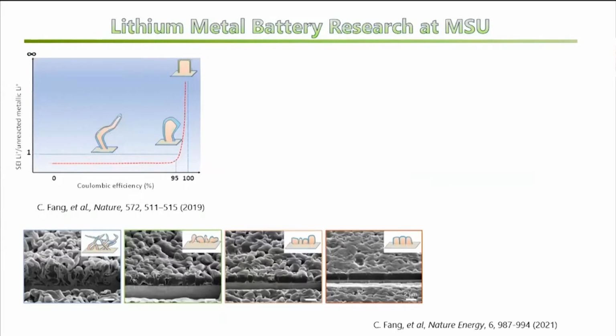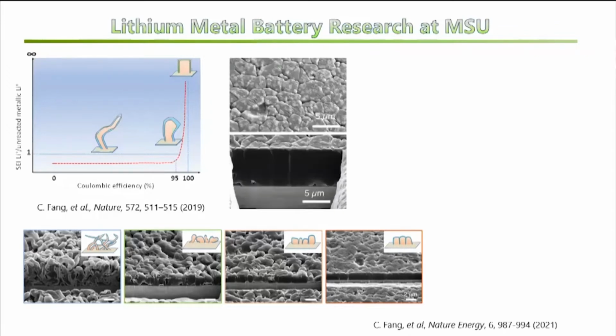Our recent research identified the stack pressure as a powerful tuning knob to precisely control the lithium growth morphology during battery operation. As you can see, by optimizing the stack pressure, we can tune the morphology from the left-hand side whiskers all the way to the fully dense lithium. And these two images show that we achieved the ideal morphology we predicted. This picture probably represents the highest level of manipulation of electrochemical lithium deposition in human history.